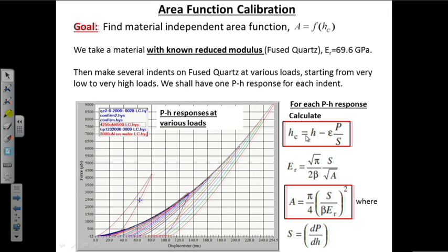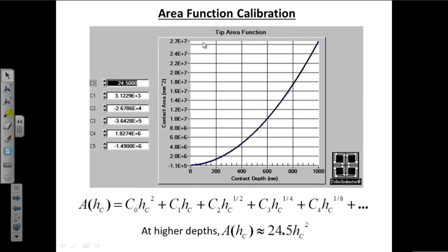So, by plotting many P-h responses starting from low load to high loads, we can calculate contact depth and the corresponding contact area from each P-h response. And we plot those contact areas as a function of contact depth for all those P-h curves, and we get this kind of response, which can be expressed in the form of a polynomial shown here, where area A, a function of contact depth, is equal to C0 hc squared plus C1 hc plus C2 hc to the power half and other higher order terms.